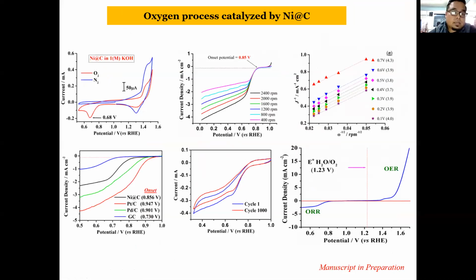So we found that our material that we have prepared is a very stable one and forms a very good oxygen reduction process, and at the same time oxygen evolution process. So this material actually acts as a bifunctional material where both oxygen reduction as well as oxygen evolution processes